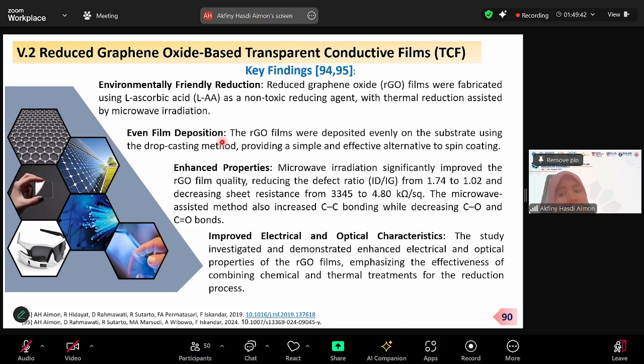And that it has good properties. So with microwave irradiation improve the property of the films, the ID/IG from 1.74 to 1.02, and the resistance is also decreased from 3,000 to 4 kilo ohm per square. Okay, the microwave method also increases the carbon-carbon bonding and reduces the carbon-oxygen bonding. And then improves electrical and optical characteristics. The study investigated and demonstrated enhanced electrical and optical properties of the RGO film, emphasizing effectiveness of combining chemical and thermal treatment for the reduction process.